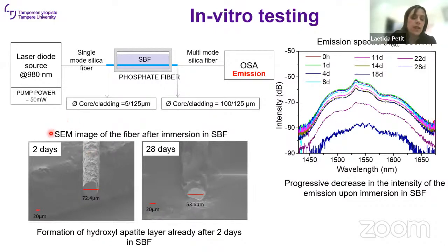So we used the scanning electron microscope to look at the surface of the fiber at different data points. So here you have the fiber after 2 days in SBF and then 28 days in SBF. And the surface of the fiber actually changed, and also the diameter of the fiber is reduced over time. So this clearly showed the reaction of the fiber with the liquid.